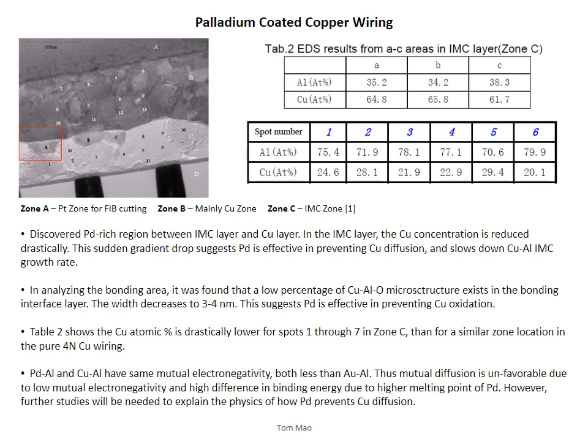When they were analyzing the bonding area, they found a low percentage of copper aluminum oxygen microstructure in the bonding interface layer, with a width of 3 to 4 nanometers, which proves that palladium is effective in preventing copper oxidation.